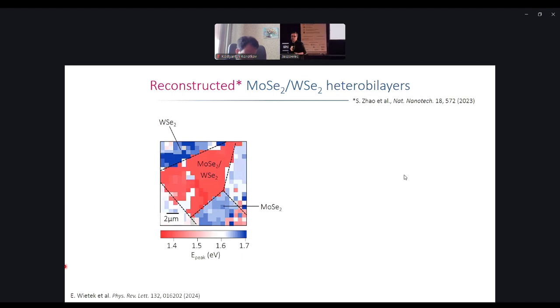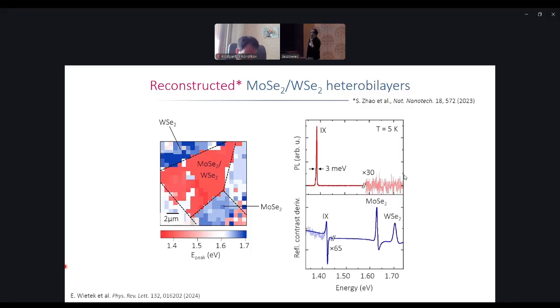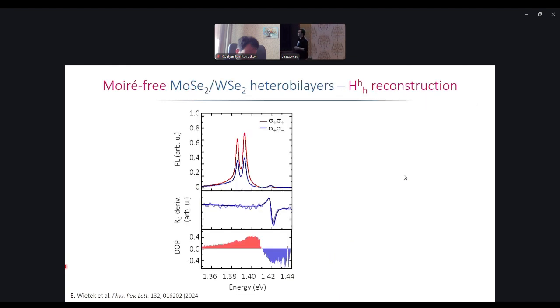Building a heterostructure, which in this particular case, for certain reasons of what is called atomic reconstruction, so that the lattices can actually arrange if the angle is very small, so you combine two lattices, that you don't observe Moiré patterns, but the system basically goes into a single registry. And in this particular case, the system can be quite simple. So there are interlayer excitons, this charge transfer you see in luminescence and in reflectance. There is no evidence of Moiré.